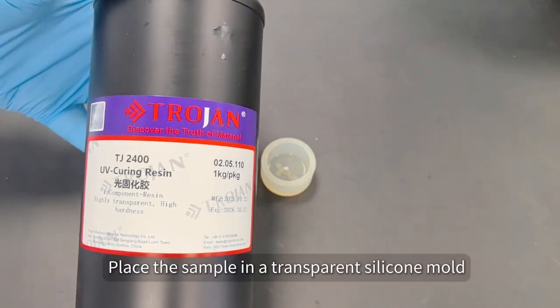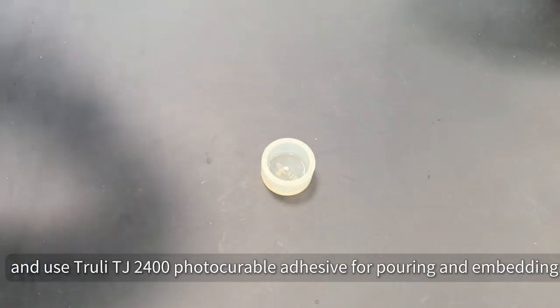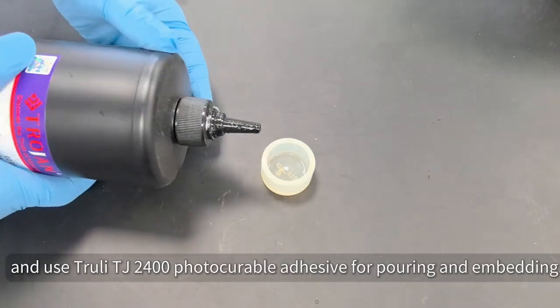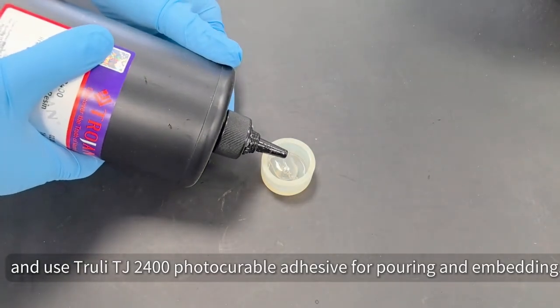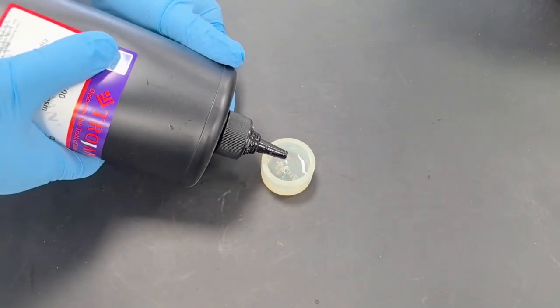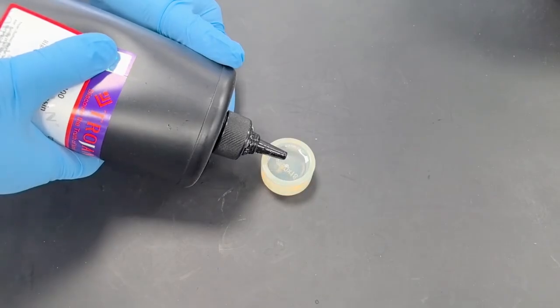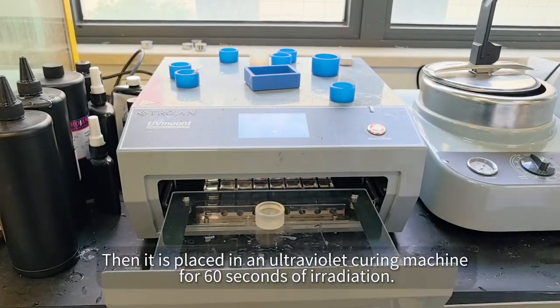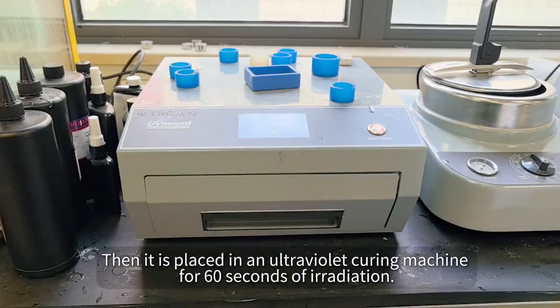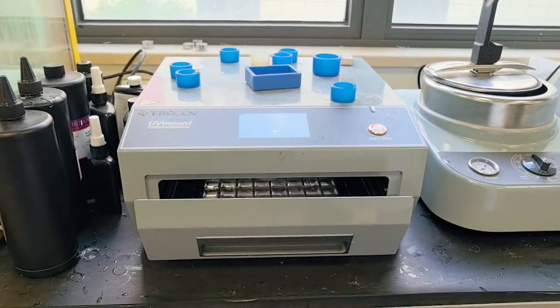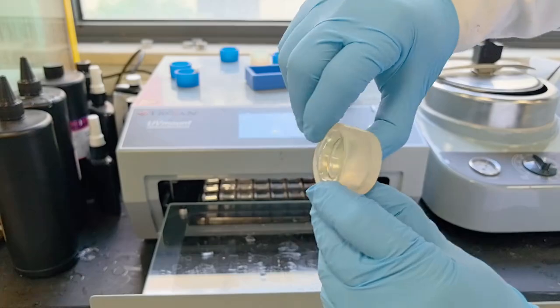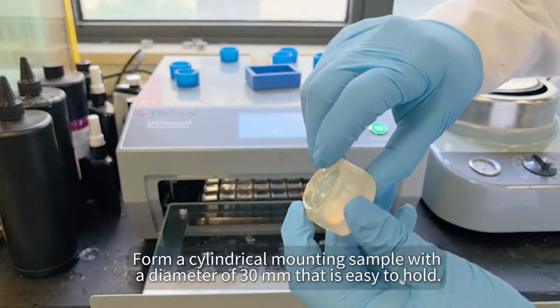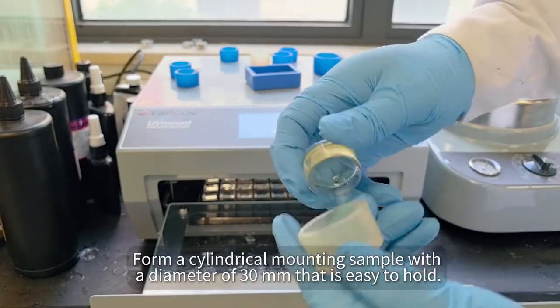Place the sample in a transparent silicone mold and use Trojan TJ2400 photocurable adhesive for pouring and embedding. Then it is placed in an ultraviolet curing machine for 60 seconds of irradiation. Form a cylindrical mounting sample with a diameter of 30 mm that is easy to hold.